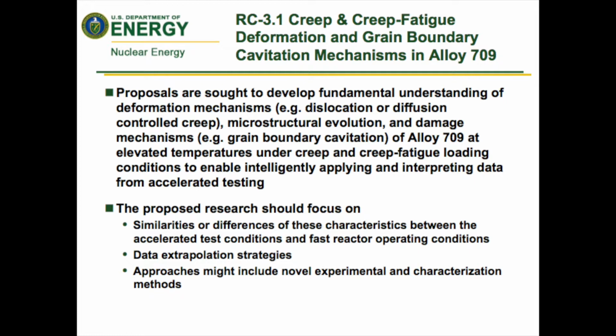creep and creep fatigue deformation grain boundary cavitation mechanism, we're looking for proposals to develop a fundamental understanding of the deformation mechanisms involved. These are things like dislocation or diffusion-controlled creep, microstructural evolution, damage mechanisms, grain boundary cavitation, for instance, of 709 at the elevated temperatures under creep and creep fatigue loading conditions to be able to allow us to intelligently apply and interpret the data from the laboratory and accelerated testing to the lifetimes that we need for the